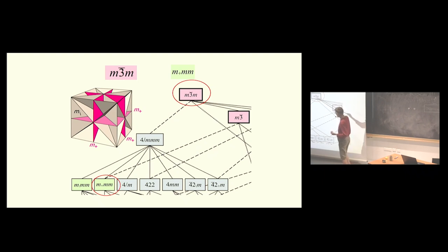So with that, we can distinguish, for example, group-subgroup relationships between this high symmetry group. We can have a species which goes to MMM, but where one of the M has a slash, or to MMM where one of the M has a cross. So these are different species because they lead to different physical situations. Because you kept different mirror planes, they are oriented differently with respect to the other elements. This has to be distinguished.